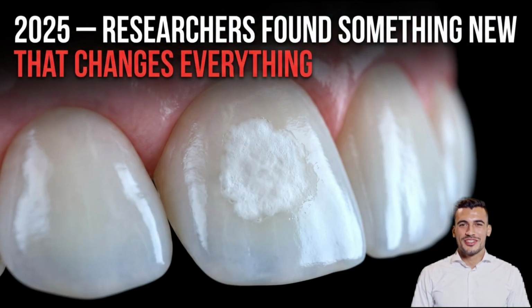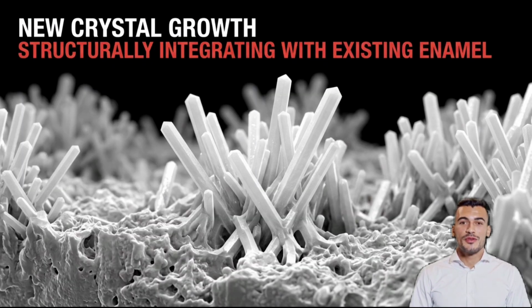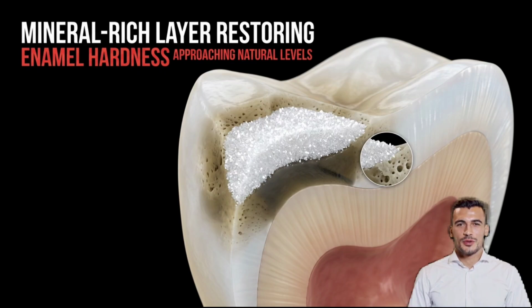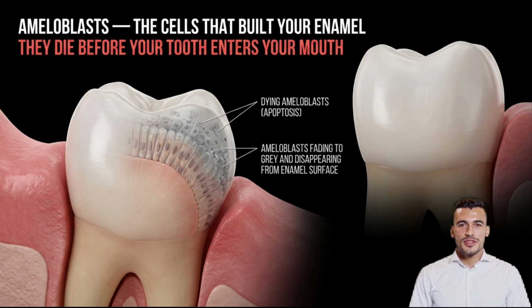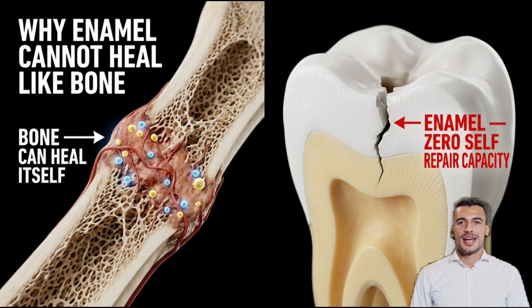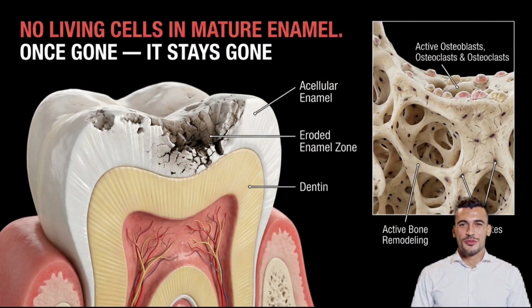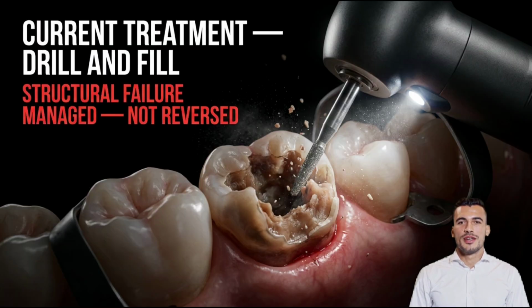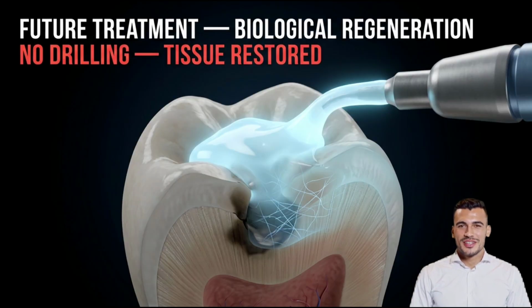There is something happening in 2025 dental research that deserves specific attention, because it may fundamentally change what tooth decay treatment looks like. Researchers have developed a bioinspired gel that can regenerate tooth enamel. Not strengthen existing enamel, regenerate it by mimicking the natural biomineralization process that forms enamel during tooth development. The gel contains amelogenin-derived peptides, proteins that guide hydroxyapatite crystal growth during embryonic tooth formation. When applied to demineralized enamel, it templates the regrowth of oriented hydroxyapatite crystals that structurally integrate with the existing enamel.